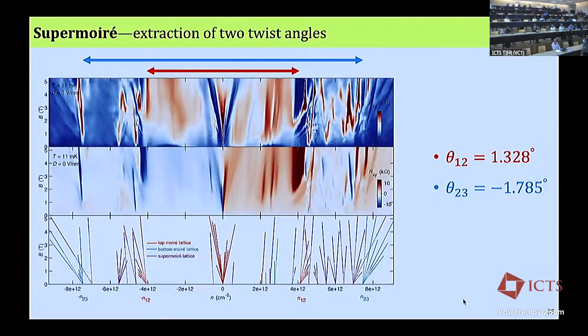Are the measurements pure DC technique or are you putting AC on top of it? This is lock-in. So when you see a hysteresis, shouldn't that depend on the amplitude? We did the hysteresis with DC.